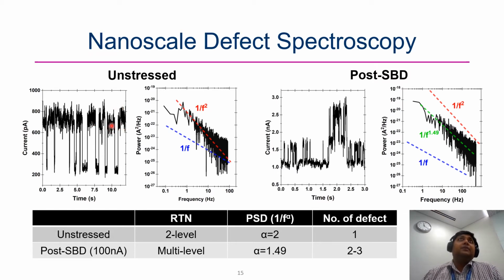In another context, for example, we can purposely create the defect. For example, in the post-soft breakdown scenario where we apply electrical stress to create the defects, you can see that we have multi-level RTN, so at least 1, 2, 3 levels of RTN, and it means that we have more than one defect modulating the charge transport.